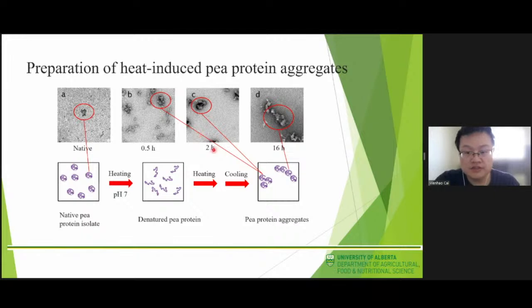Previous research suggests that thermal treatment unfolded pea protein molecules to expose the hidden active groups, which then interact with each other to form aggregates. And the elongation of the pea protein aggregates was observed with prolonged heating time, and longer strips with the length of 100 to 115 nanometers were formed after 16 hours of heating treatment.